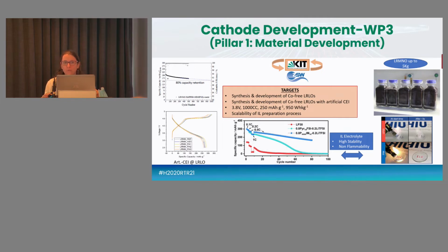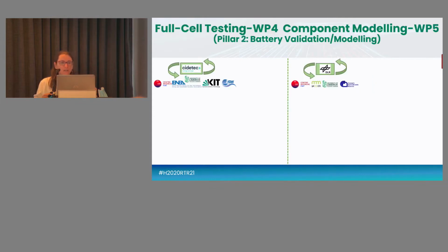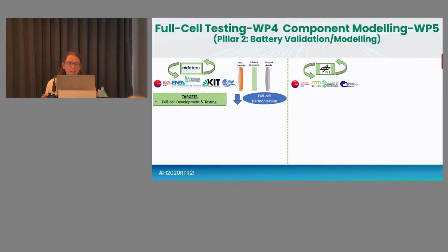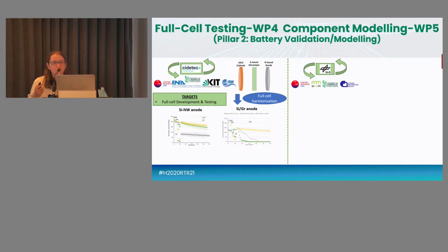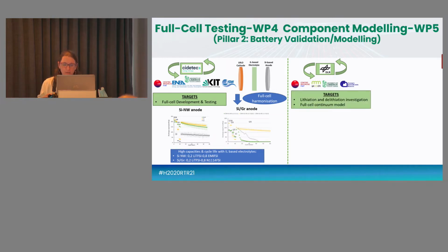At the moment, we are able to provide to the partners a cathode of up to 5 kilograms for larger scale production. Regarding work package 4, the full cell testing, the leadership is with CIDETEC, which is working on the full cell harmonization with the anode, the cathode and the electrolyte that we are providing them. At this stage, they are comparing the performance of the silicon nanowires based anode with a more standard silicon graphite based anode, to understand, at different currents, the performance of our anode. And again, the most promising formulation of the ionic liquid electrolyte is the same that we observe within the other work packages.